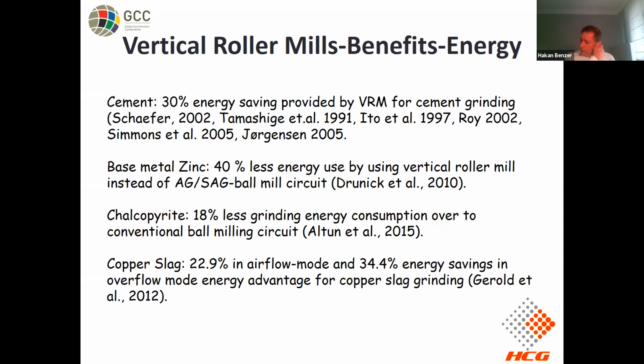We had a chance to work with the VRM plant of Loesche company for more than 6 months in Turkey. We had the chance to evaluate different ore bodies, different mineralogies, and we observed that at least 18% less grinding energy consumption can be achieved compared to a conventional wet ball milling circuit.